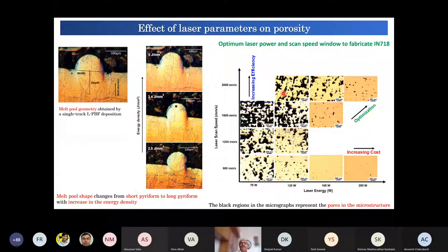And what we require is to generate a map of laser scan speed and laser energy and see where we get the most optimal condition or the tolerable level of porosity, because we also have to optimize the cost. If we go for a very high energy laser, then it will increase the cost and sometimes it may become techno-commercially non-feasible. So we have to take into account the optimization of porosity, and what the tolerance level is. Again, that requires another set of investigation that will tell, in a statistical manner, what is the tolerable level of porosity for different components.